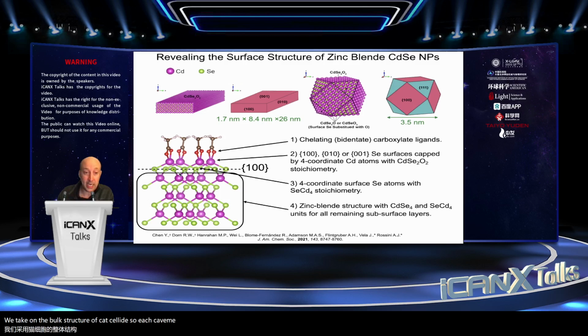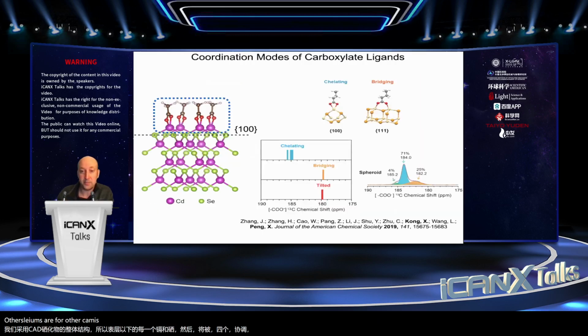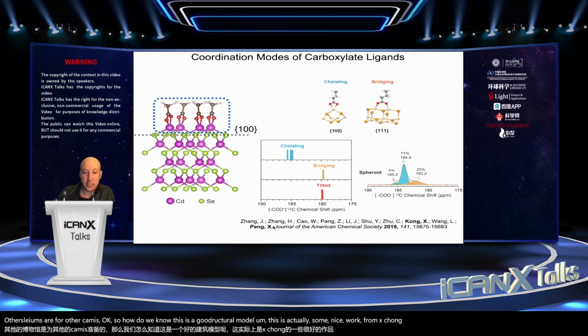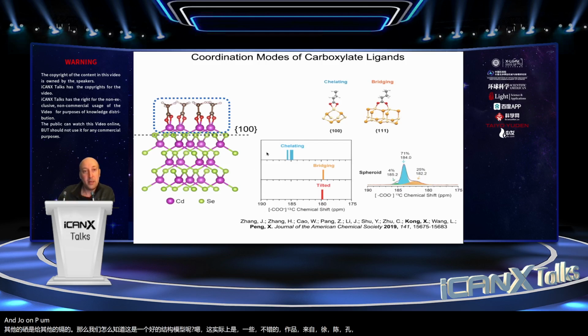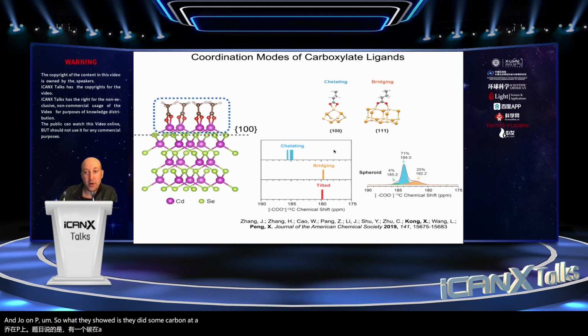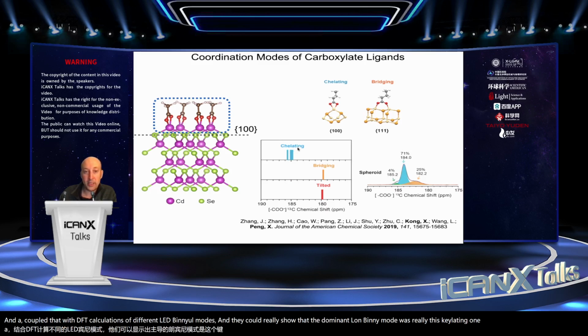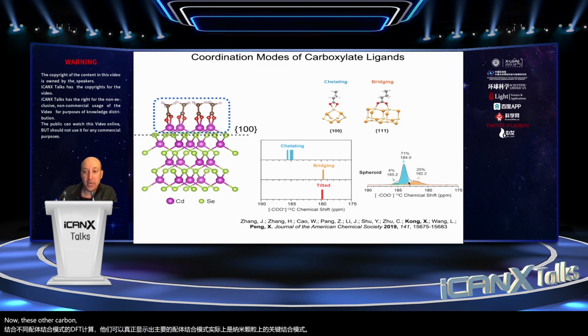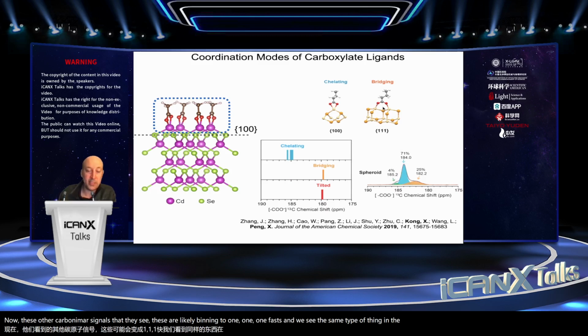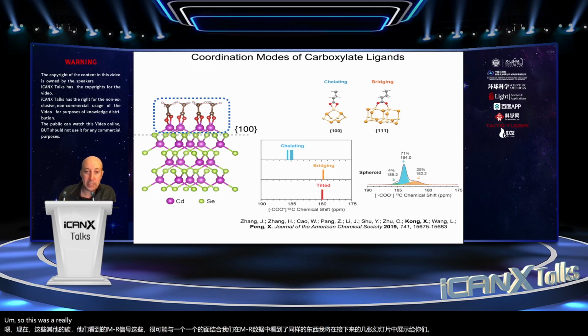So each cadmium and selenium below this surface layer is then going to be coordinated by 4 other seleniums or 4 other cadmiums. Okay, so how do we know this is a good structural model? This is actually some nice work from Shuchen Kong and Xiaogang Peng. So what they showed is they did some carbon NMR experiments and FTIR experiments and coupled that with DFT calculations of different ligand binding modes. And they could really show that the dominant ligand binding mode was really this chelating one on the nanoparticles. Now, these other carbon NMR signals that they see, these are likely binding to 111 facets, and we see the same type of thing in the NMR data that I'll show you on the next couple of slides. So this was a really nice paper.